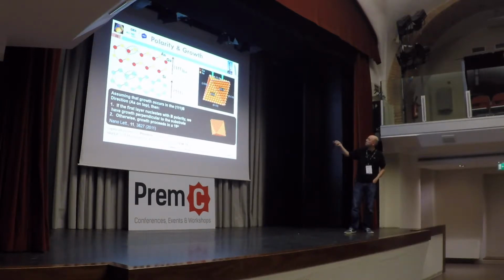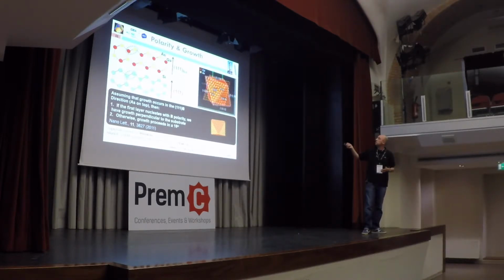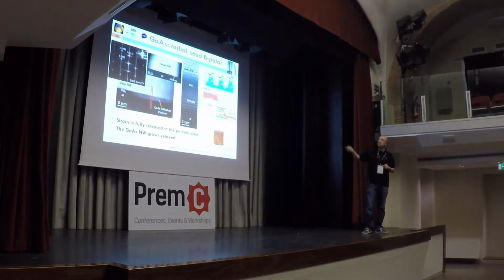So if you have this octahedra here, imagine that the first nucleation seat on top of your substrate is terminated in arsenic, then you will allow the growth of a vertical, really nice nanowire. But what happens when this is inversed? If the top layer is terminated in gallium, we cannot grow vertically, but we are allowing 3 other facets at 19 degrees that are terminated in arsenic, and it will allow the growth not in the vertical direction, but in some other angle direction. Typical nanowire.